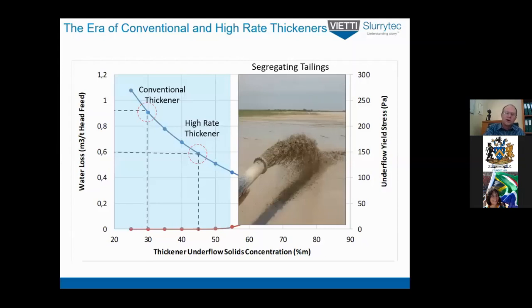And so, if you were a typical platinum miner or a gold miner, you would say, well, at 40% solids concentration, you've got no yield strength. But this is because in diamonds, the top size going to tailings is quite coarse. It can be up to 1 millimeter in some cases, but generally about 500 microns. So when you've got a slurry at 500 micron top size at about 40% solids, it's still quite watery. So just looking at the two unit processes there, conventional thickener going down to high rate thickener. In the case of diamonds, with a conventional thickener, you get about 30% solids out the bottom. High rate, you can easily get 45%. But if you look at the rheology of that underflow, it's still pretty watery. It's got no yield stress. So it behaves as a Newtonian fluid.